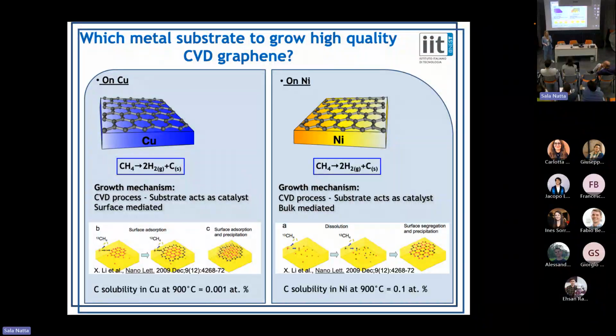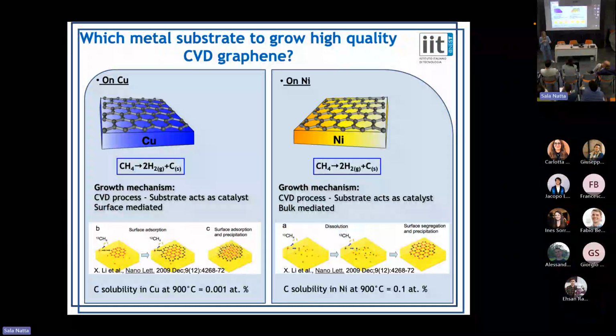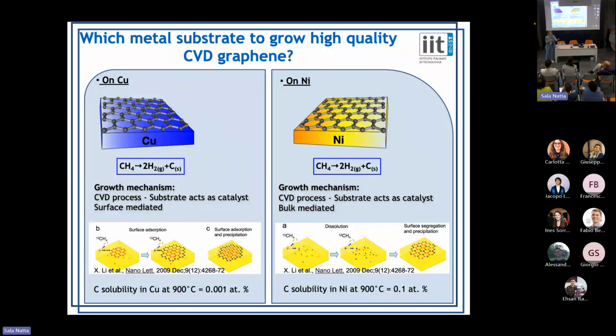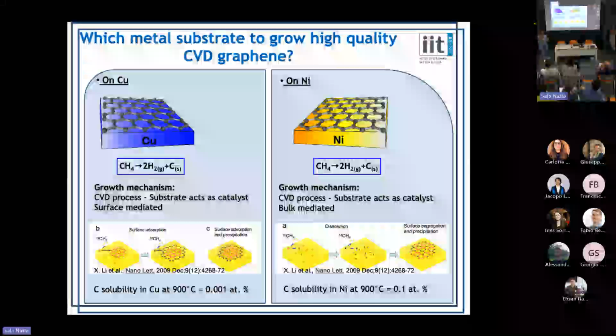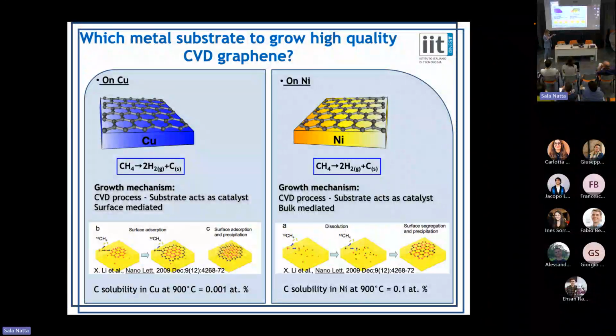No? If it's 99.9, you think, oh, then you almost have no foreign atoms. It doesn't, no, it's not true. For making a single layer, it's more than enough, even for making many more. So you usually prefer to work with very pure materials to avoid this. But it's not always true, because during my career I also discovered that sometimes having it a bit dirtier helps some processes. So we can grow nowadays.